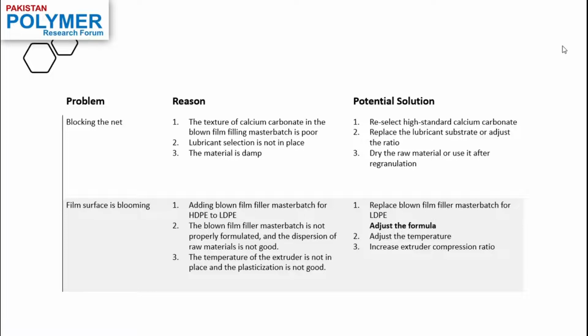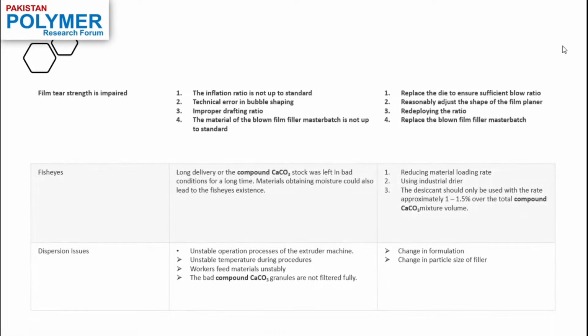Other problems that occur include the film tear strength being impaired. Well, this problem is more relevant to the blown film, because if the inflation ratio or the drafting ratio is not proper, not in place, you might get a film that has an impaired tear strength. So it's important to adjust the ratio of the wind-up velocity and the exit velocity of the filament, as well as the inflation ratio of your blown film.